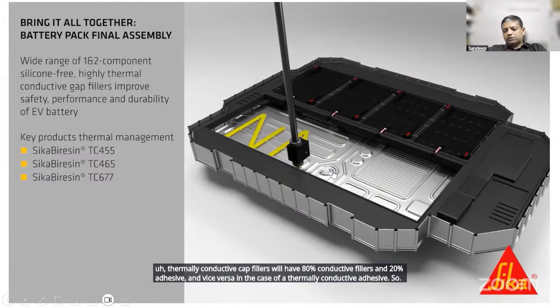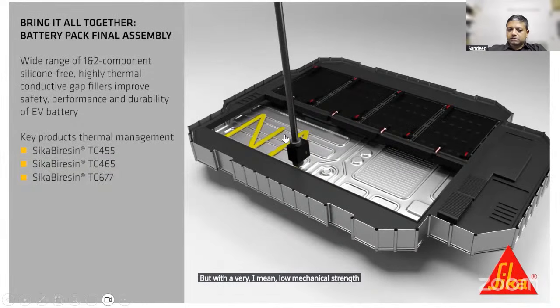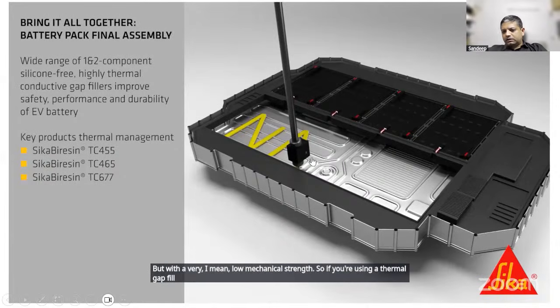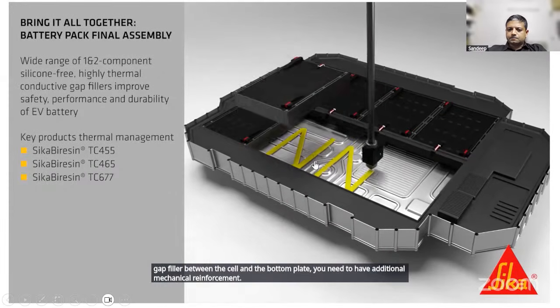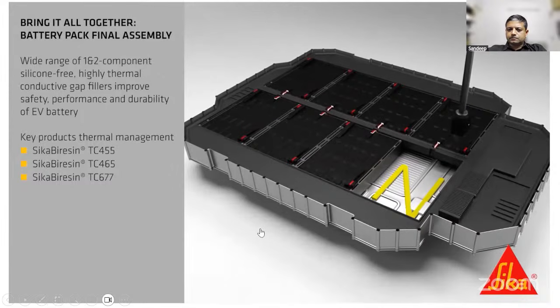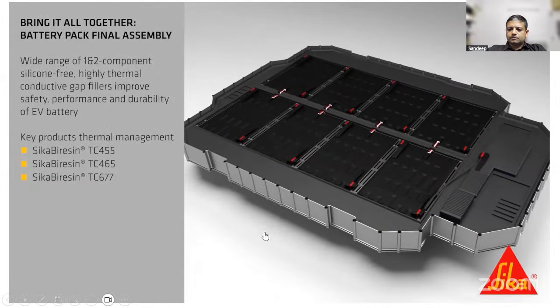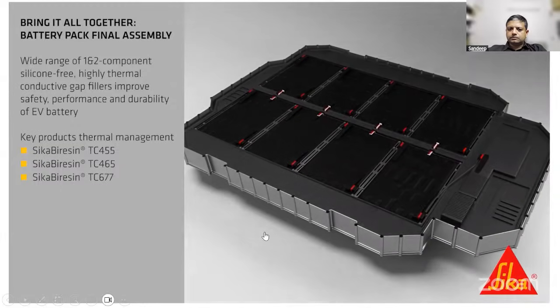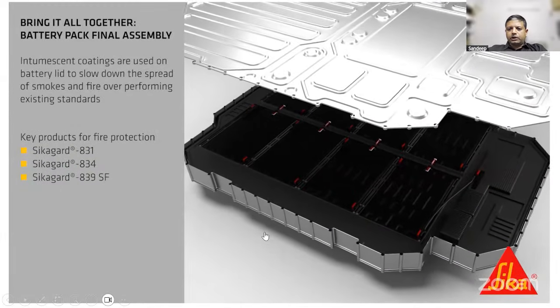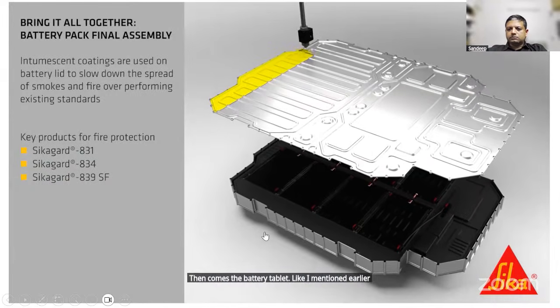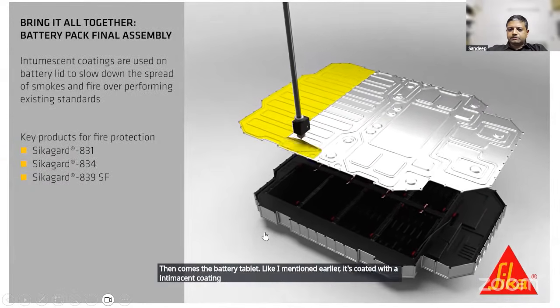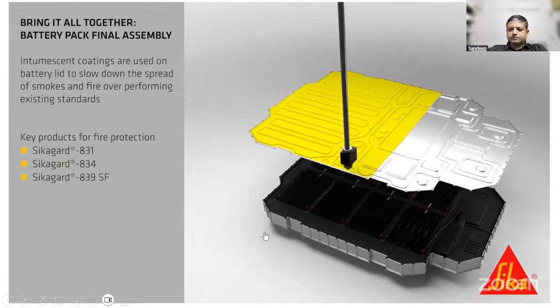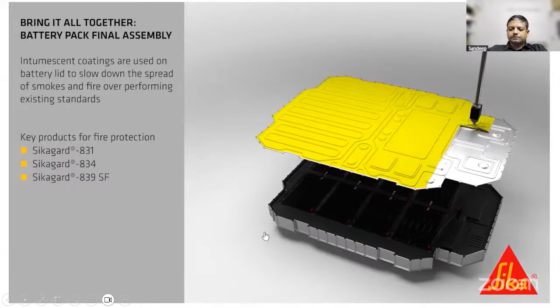In this case, thermally conductive gap fillers can go up to 3.5 watt per meter Kelvin of thermal conductivity, but with very low mechanical strength. So if you're using a thermal gap filler between the cell and the bottom plate, you need to have additional mechanical reinforcement. Then comes the battery top plate, which, like I mentioned earlier, is coated with an intumescent coating from the inside. Then you have these.